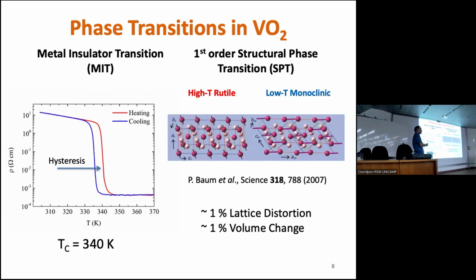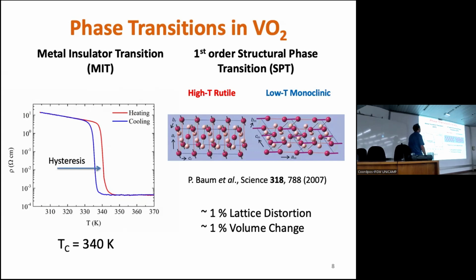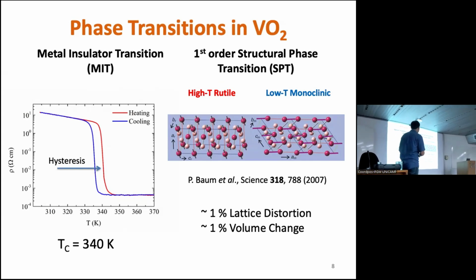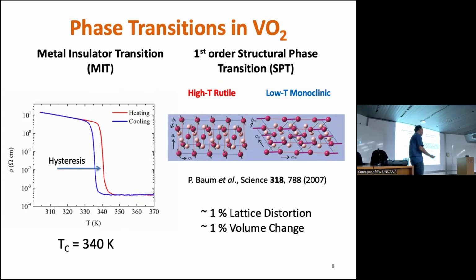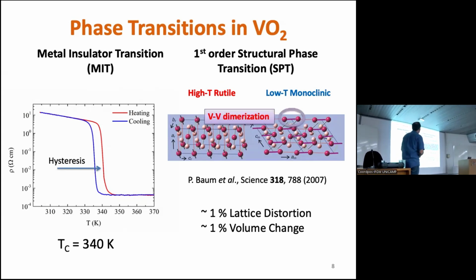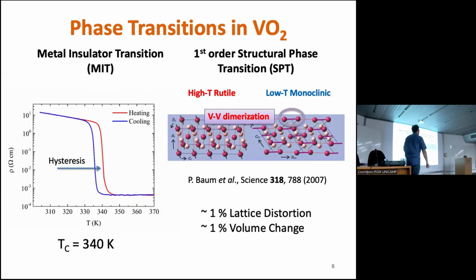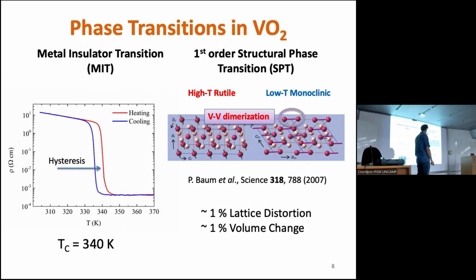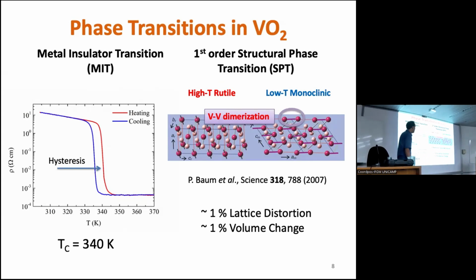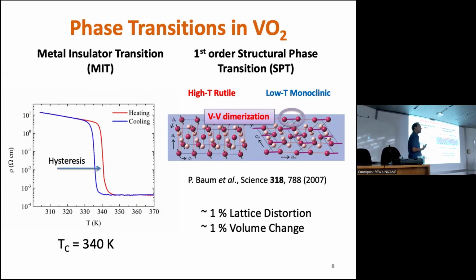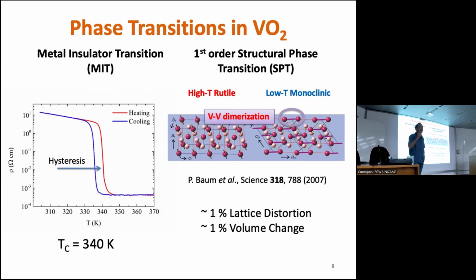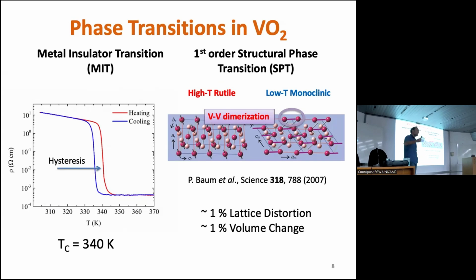The transition temperature here is kind of high, 340 Kelvin, 68 Celsius. There is a structural phase transition. It goes from a rutile structure at high temperature, and then it becomes monoclinic at low temperature. This is a non-magnetic oxide, so there is nothing magnetic here in principle. The distortion is about 1%, so a 1% volume change, which is quite big. This happens because there is a dimerization between these vanadium atoms when you change the temperature. Trying to understand the physics behind the reason why there is a phase transition in this material is still, even after many years, an open debate.